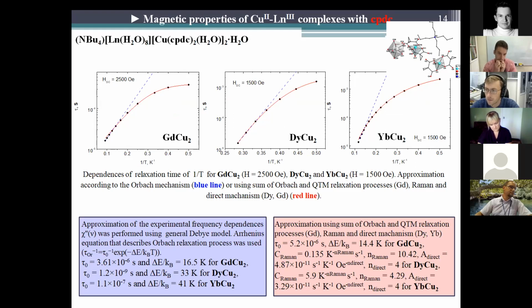First, comparing the obtained values of barriers, it can be concluded that the best relaxation characteristics are possessed by copper-dysprosium and copper-ytterbium compounds with metal ions that are not linked to each other by bridging groups. For the standard coordination polymers, slow magnetic relaxation is completely absent, which can be explained by the presence in this compound of significant magnetic interaction between metal ions.